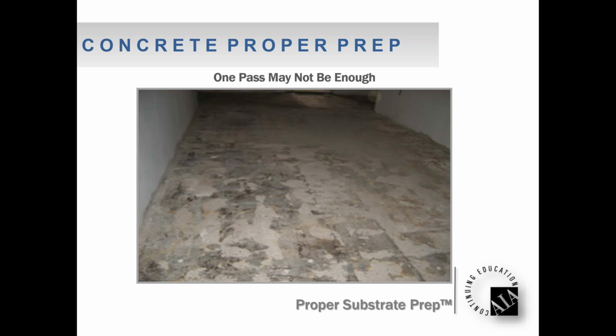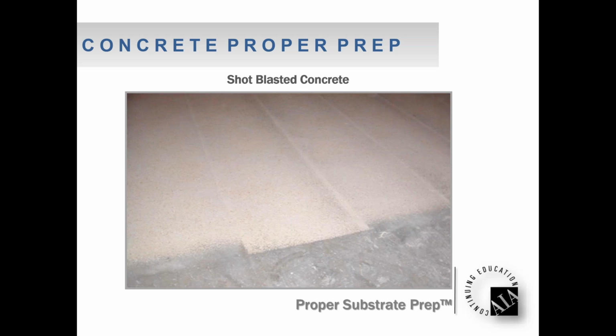Sometimes one pass isn't enough though. Might take repetitive passes to remove all the contamination. Okay, here's a picture of concrete that's been blasted. You can see in the forefront of the picture areas that haven't been blasted. Obviously, center to the top, you can see where the blaster has hit. It's very clean, it's very open, it's very porous. It's easy to see where the machine hasn't hit yet.